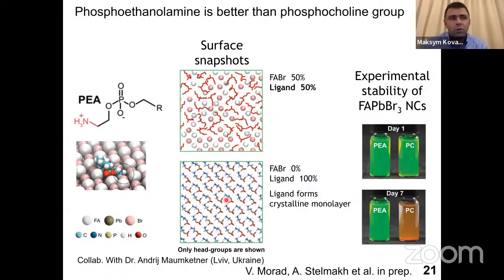And so this correlates well with subsequent experiments. So what experiments have shown is that indeed, if you take exactly the same organic rest here and just compare the PEA group with the phosphocholine group, like shown here, on day 1 these colloidal solutions will look similar, but a few days later you'll notice a big difference, because the PEA-based ligand desorbs much slower than the one which is phosphocholine-based. Basically, in good agreement also with the simulations showing this much more stable binding.